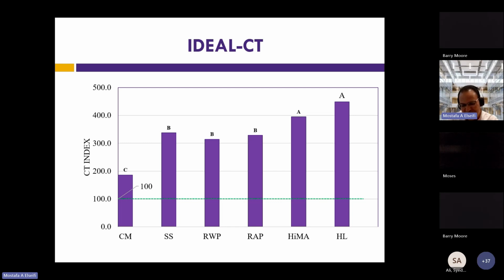Like in my previous studies, when you mix binder, for example, with shingle or with other types of additives, it doesn't react easily. And if you end up with a filler, it may affect the flexibility of your binder, which may reduce your CT index. Most of the studies, when they use plastic, want to grind it to passing 200, and that will increase the cost of the mix tremendously. At the same time, they want to blend it with the binder and then use the blend in the mix. In my opinion, that may not be the best approach. Why? Because first, the amount of plastic that you can use is minimal, so you don't really solve any problem. And at the same time, you may end up negatively affecting the flexibility and the rheology properties of your binders.